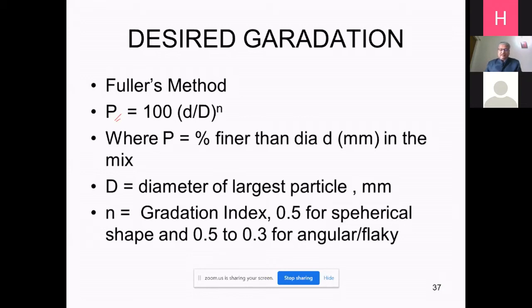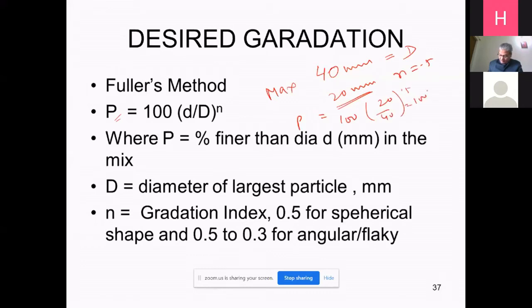Let us take one example where we have a material in which the maximum size is 40. So this becomes our capital D. And I want to know what the material passing 20 mm should be. And n may be taken as 0.5. So P is equal to 100 times (20 upon 40) to the power 0.5. That is 100 into 1 by root 2, so this is 100 into 0.71, which comes out to be 71%.